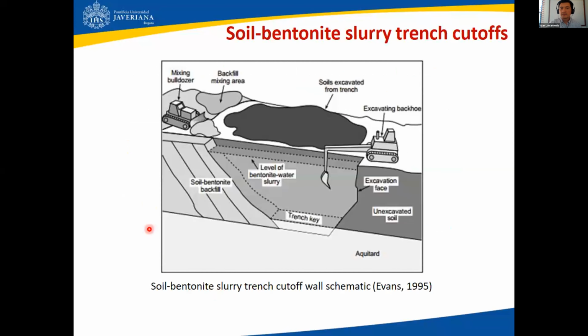So in both cases, though, the bentonite is typically sodium montmorillonite expansive clay. What you're looking at here for soil bentonite cutoffs is a schematic of the typical construction process of these types of systems. So you have here a backhoe that is digging the trench up to a certain depth. At the same time, a slurry prepared with bentonite and water, typically 5% or so bentonite, is prepared and is filling the trench to avoid collapse of the trench and the excavation itself. And it's permitted to settle for some time.